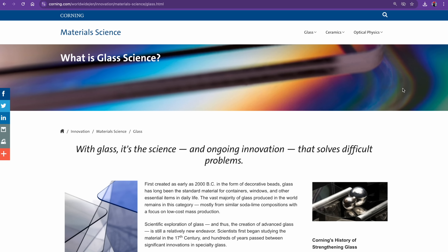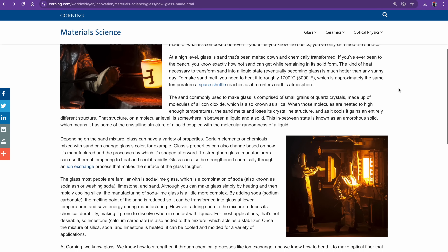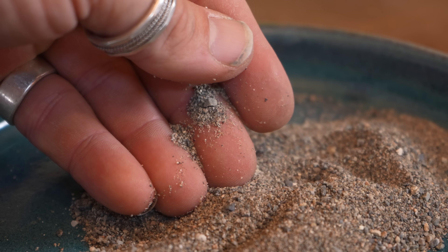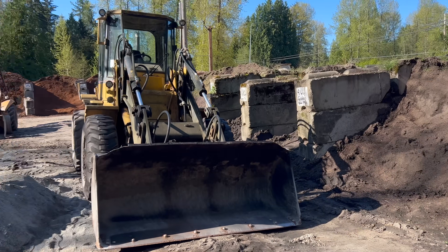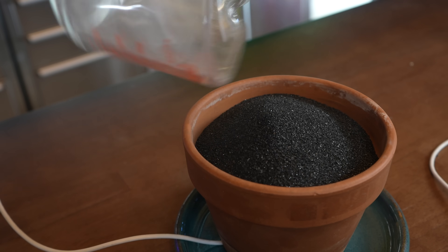Also super fragile — several arms have already broken off, so I want to fix that. After some reading on how glass is formed, turns out uniform grain size is critical to proper and equal melting. And you'll notice this play sand was more diverse than a Netflix show. So I drove to a local landscaping supply and after some digging around found some fine grain black sand. Filling the pot with preheated black sand, the results were promising.